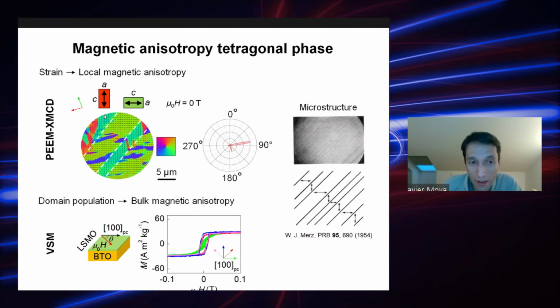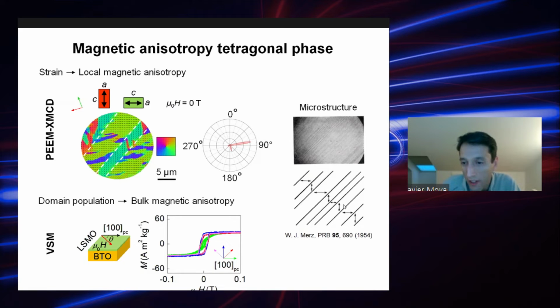And in this region, which is another type of domain, where the magnetization is either up or down, this corresponds to a region in the substrate where the c-axis is basically in the vertical direction. So this correlates very nicely with the X-ray data and the type of microstructure that we expect. So we can say that we can control the anisotropy with the strain and stress coming from the substrate.